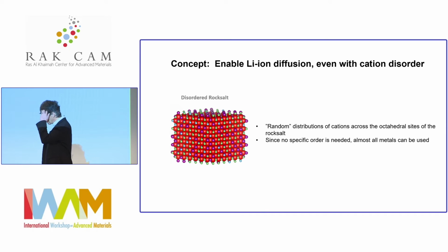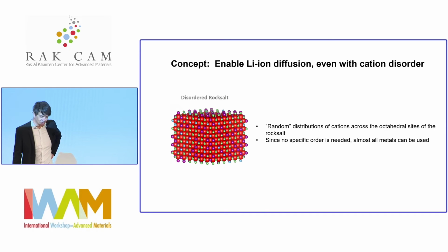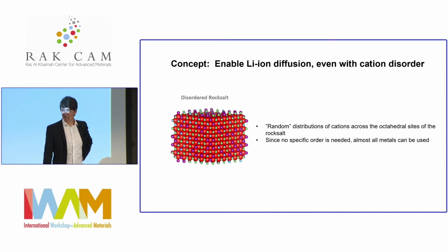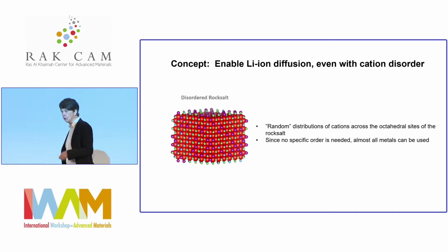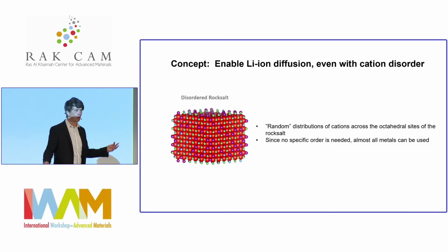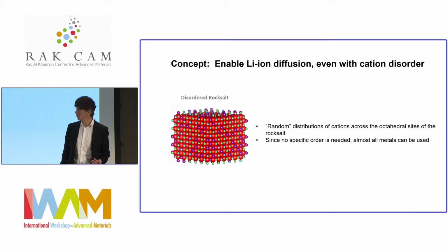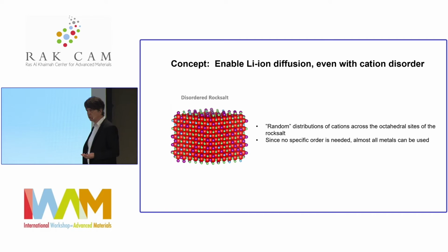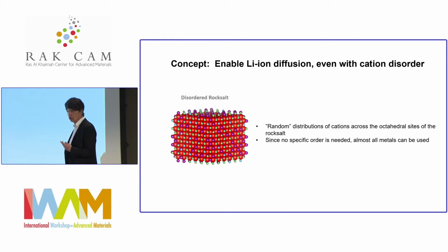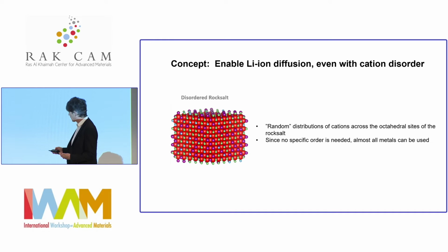So the other strategy, which it took us a while to give in to, was, well, you could just learn to work with cation disorder. You could accept that the ions move all over the place and see if you can still do decent diffusion, and that led to what's now called a class of disordered rock salts. So the class of disordered rock salts are essentially a close-packed oxide like layered materials, so they are crystalline, but the cations are just disordered over the octahedral sites.